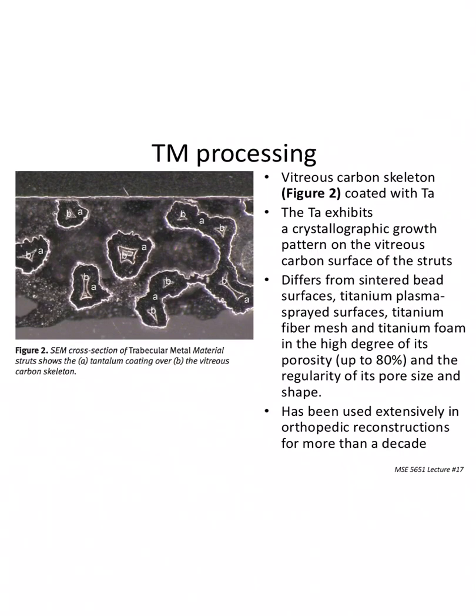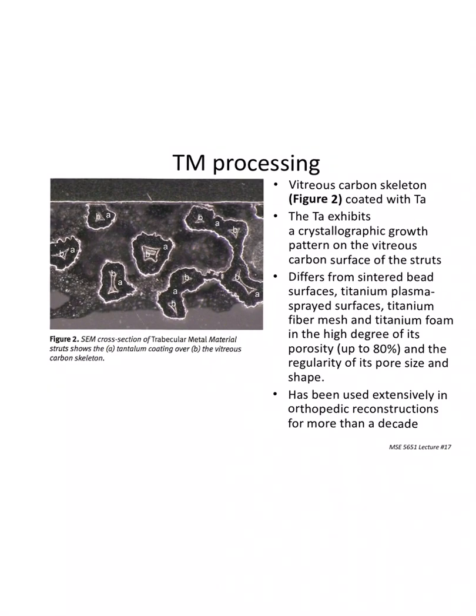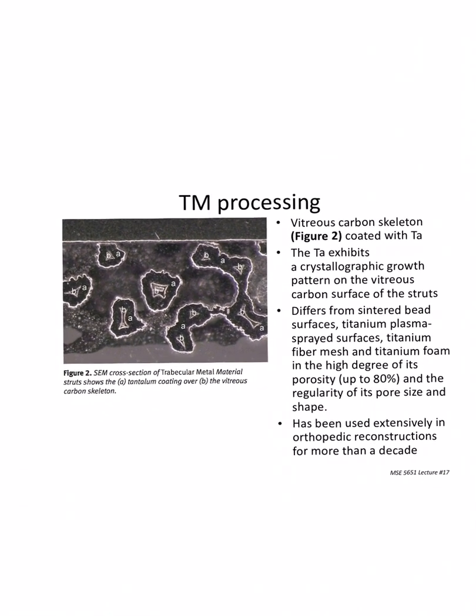You've got the formation of a vitreous carbon skeleton. So you take, and we talked about this before, you take polymer, you heat it up in inert conditions, it doesn't volatilize, it makes carbon. All right, there's no oxygen there, and if you heat it quickly, then you don't let it tear apart itself. All right, and you can make carbon, or you can cross-link it, and then it won't volatilize at all and makes carbon. So you take a sponge, heat it up, and you make this vitreous carbon skeleton, and it ends up being coated with the tantalum.